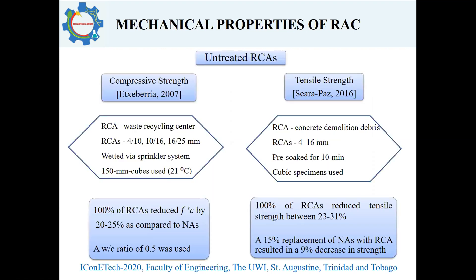Mechanical properties of recycled aggregate concrete. Untreated recycled concrete aggregates were used to produce recycled aggregate concrete specimens to test the compressive and tensile strength. Recycled concrete aggregates from a waste recycling center were used as a 100% replacement, and it was found to reduce the compressive strength by 20 to 25% as compared to natural aggregate concrete. Another study mentioned that pre-soaking recycled concrete aggregates retrieved from demolition debris resulted in a 23 to 31% decrease in tensile strength when 100% recycled aggregates were used.